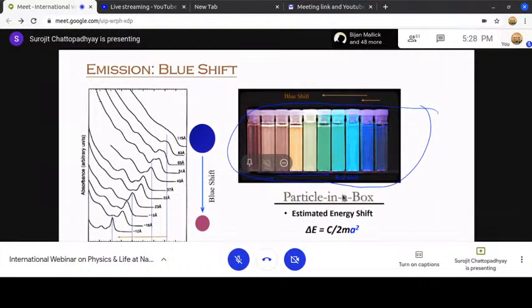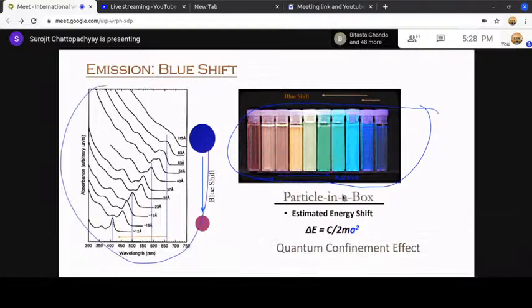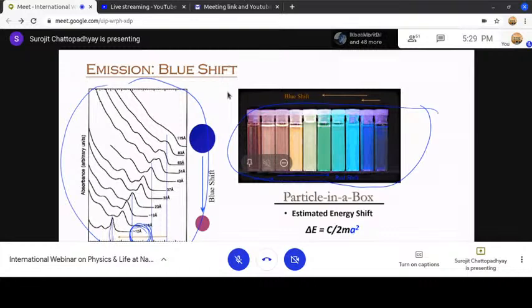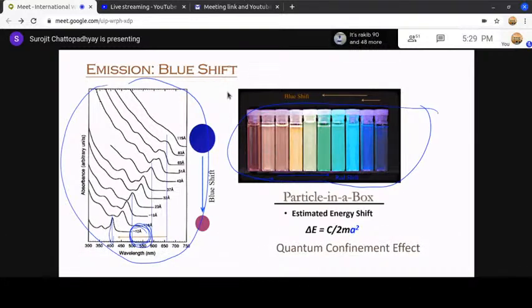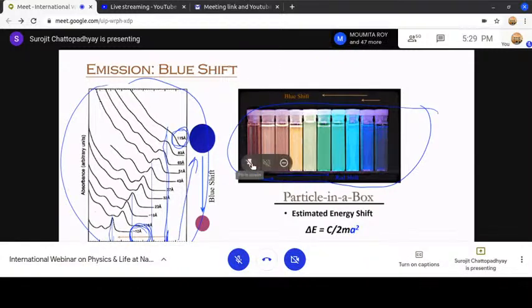If you note, all these materials, we have plotted the absorption. These materials will absorb light. So if you plot the absorption as a function of wavelength, then you see a small quantum dot, which is around, say, 12 angstrom size, that means 1.2 nanometers, they have absorption peak around 400 nanometer. If you convert 400 nanometer to energy, you will see that's around 3.2 electron volts or something like that. Now, if you make the same material bigger, so you go this way, you see the biggest nanoparticle that we have is around 150 angstrom, which is around 15 nanometers, and they have absorption band around 650, which is like 2 eV.